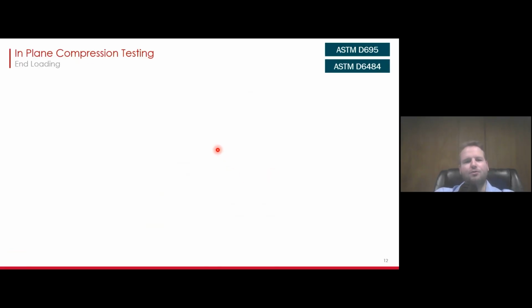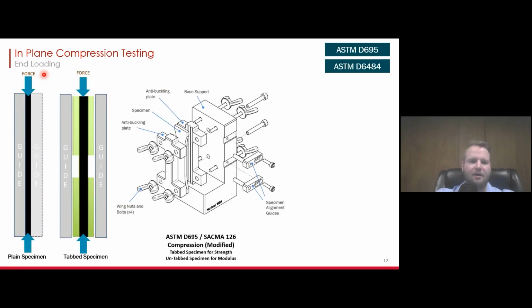So now we're going to move on to compression testing. We're still in the in-plane direction, so direction number 1 or 2, and we're using end loading to initiate the force into our specimen. Most common standards for that are ASTM D695 and ASTM D6484. Kind of looks like this. So you have guides around your test specimen, which is the black part here in the middle. And like I said earlier, the force is being initiated at the ends of the specimen. So you get some force here. Typically, you come down with a compression platen from the top, and then your specimen is supported on the bottom.